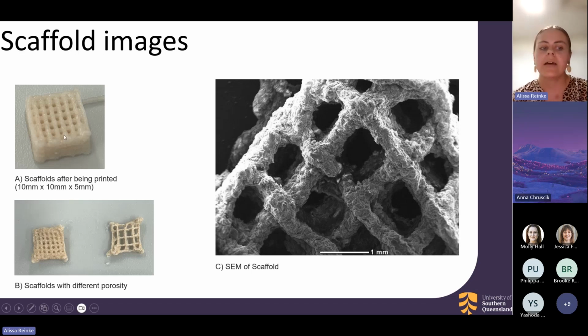So it's about 1 centimeter by 1 centimeter by about 0.5 centimeter. And in this image here, if you were to touch it, it would be like jelly. So it's still quite soft. Once it goes through the evaporation process, this is what it looks like here. So it does change shape slightly, but it still maintains that porosity. And this is just a different porosity scaffold. So testing a number of different porosities at the moment.